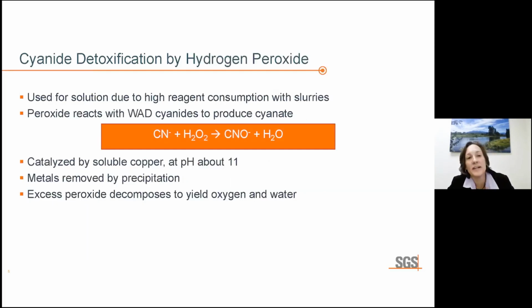Moving on to peroxide, this is used more for solutions containing cyanide because there's really high reagent consumption in the presence of slurries. The peroxide also reacts with the weak acid dissociable cyanides to produce cyanate. Again, this is catalyzed by soluble copper. It works at a pH of around 11. Metals can be removed by precipitation, and any excess peroxide decomposes to yield oxygen and water.